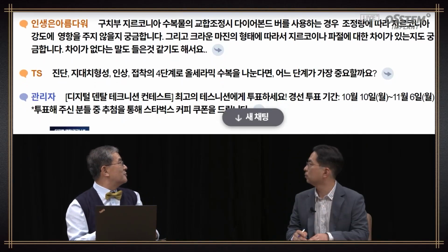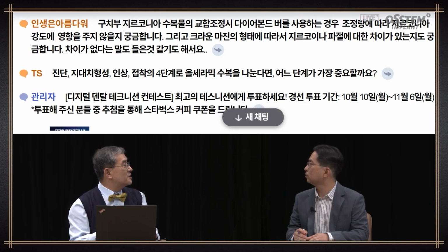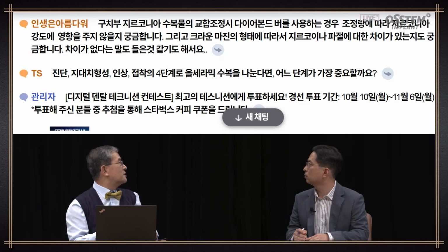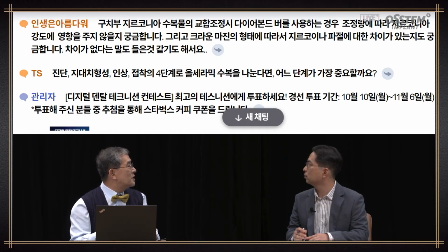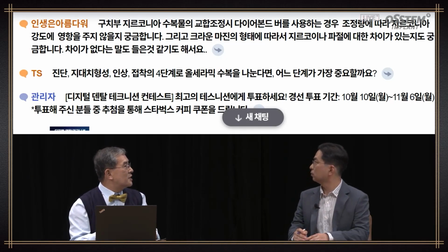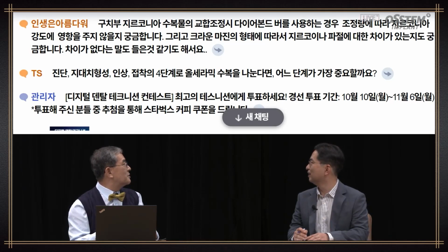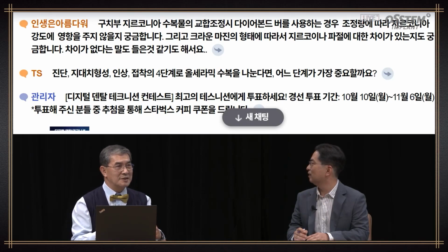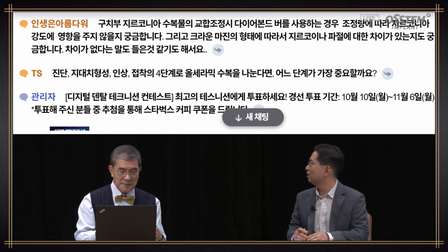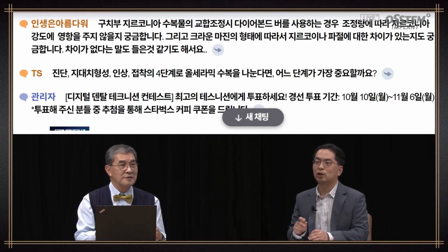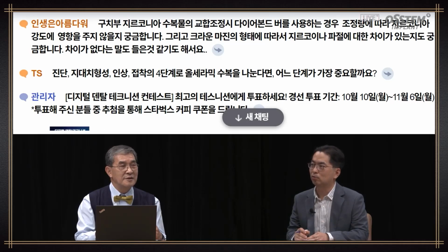When I adjust the occlusion of a zirconia restoration in the posterior area, if I use a diamond burr, depending on the amount, it can perhaps affect the strength of zirconia. Depending on crown margin contour, is there any potential relation with a fracture of zirconia? I've heard that at times it doesn't matter. In the case of a diamond burr, it does not really matter.